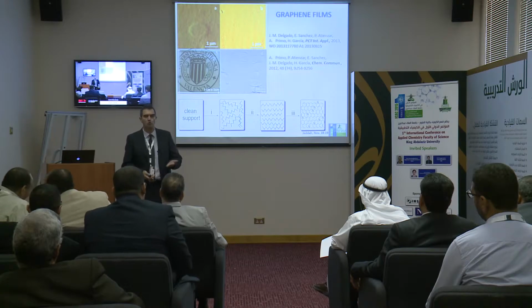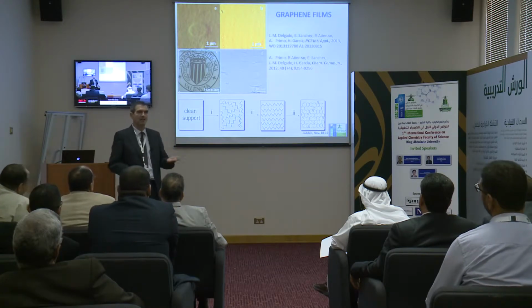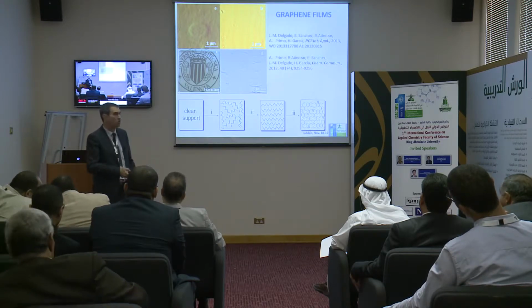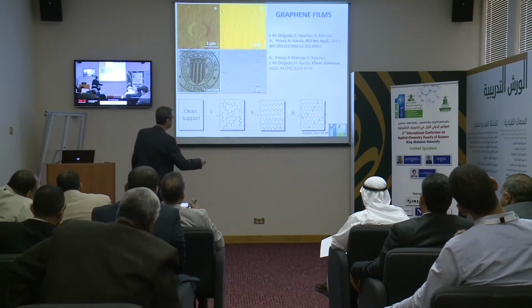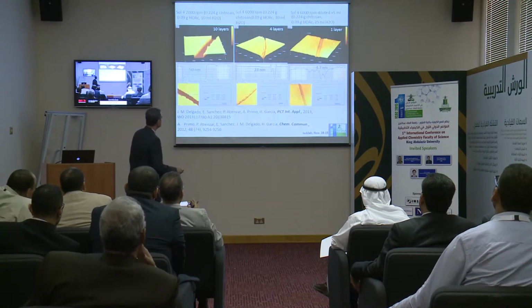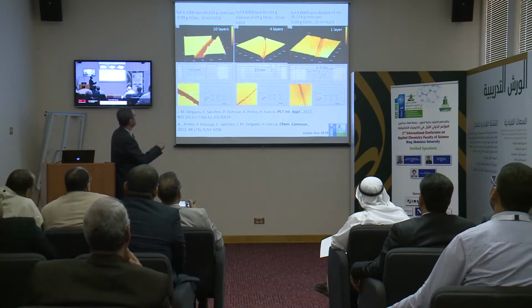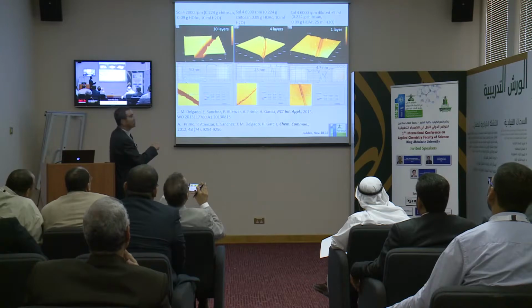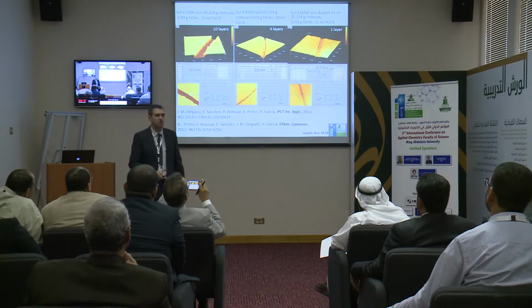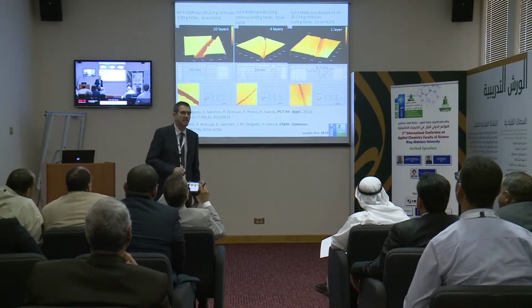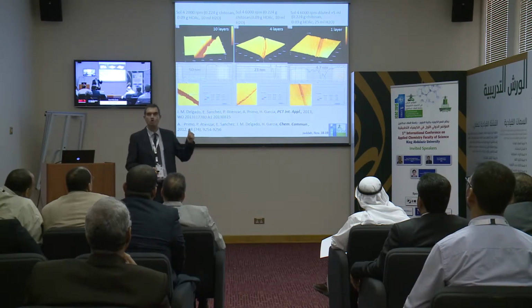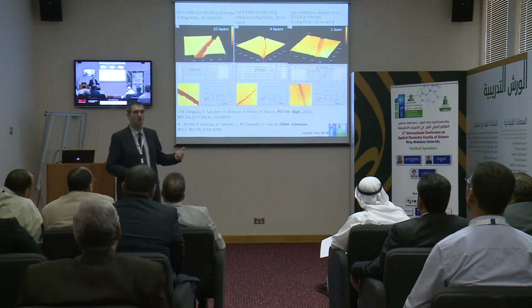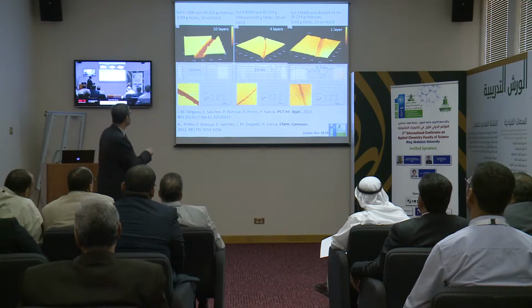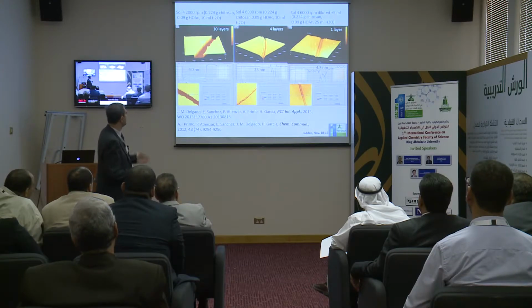This precursor is annealed. Annealing means to put it under humidity for a long time at a certain temperature. So we think that the annealing allows the ordering of the chains, and then we pyrolyze, and then we have the graphene. These are the images of the precursors. Look how nice the films are, because these precursors are called filmogenic. They are polysaccharides, but not all the polysaccharides can do this. Only a few polysaccharides can make this type of films, and these are the filmogenic ones.